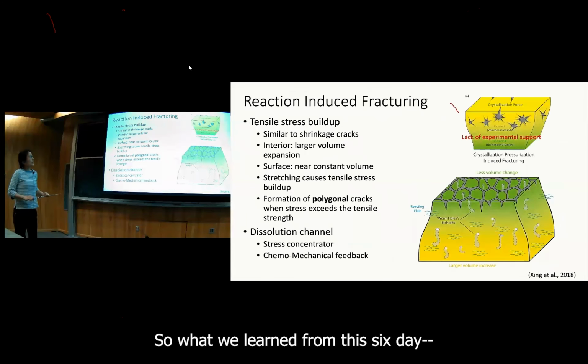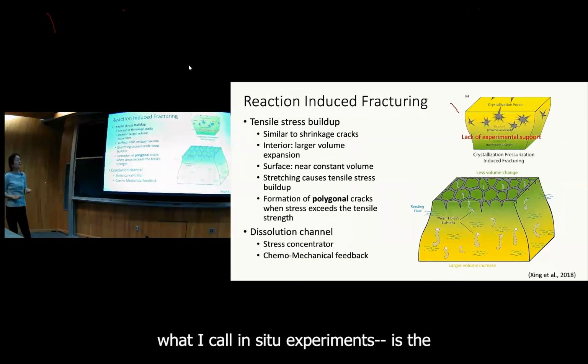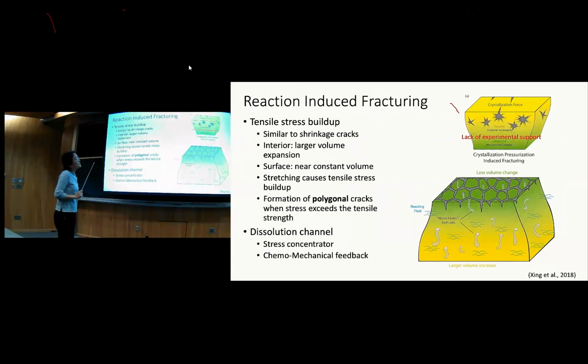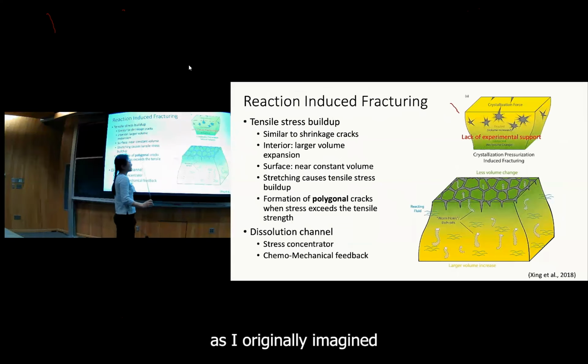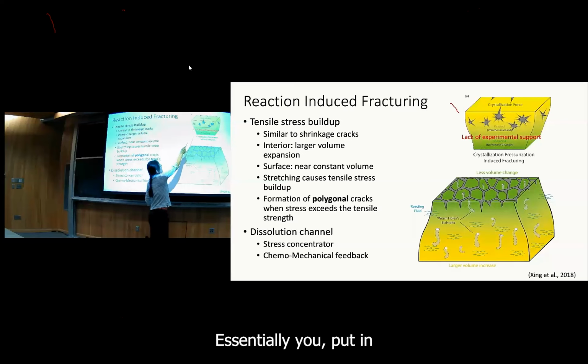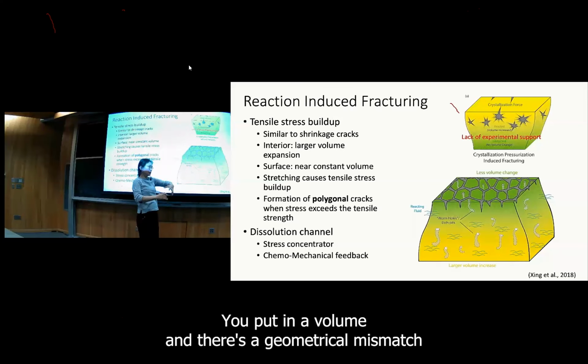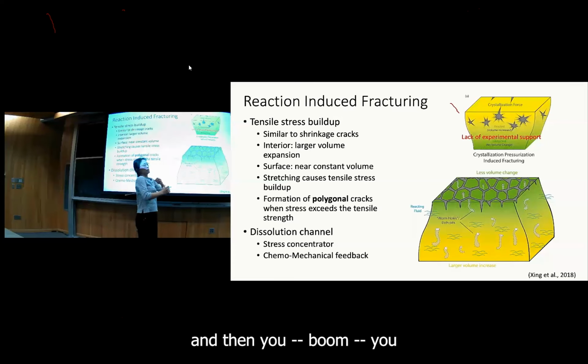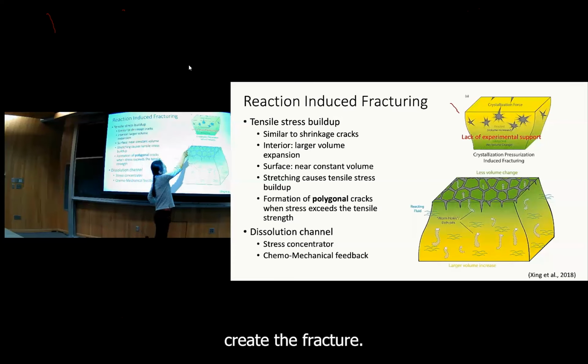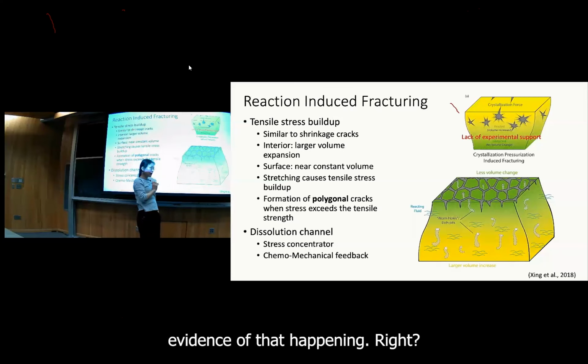So what we learned from this 6-day, what I call in situ experiment, is the crystallization pressure as I originally imagined. Essentially, it's more like bursting a balloon: you put in a volume and there's a geometrical mismatch and then you boom, you create the fracture. That we have no evidence of that happening, all right?